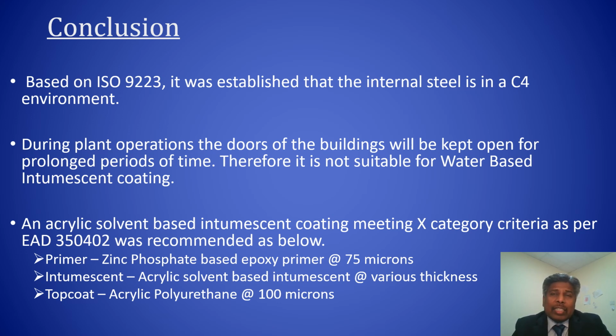Now, one of the challenges that we have addressed here was that there is no clear guidance to state that if it is a C4 environment, a water-based intumescent shall not be used. There was no direct guidance either from industry bodies or from standards to state that a water-based intumescent shall not be used in a C4 environment. So this work that we have done is basically to show that we can identify the environment in places where the project detail is not very clear, but it also clearly defines that a product and a system, including the primer, mid coat and the top coat, tested to X category shall be used in a C4 environment. Thank you very much.